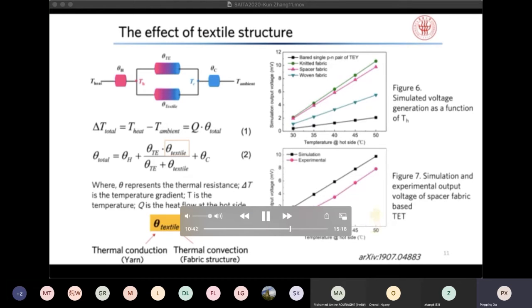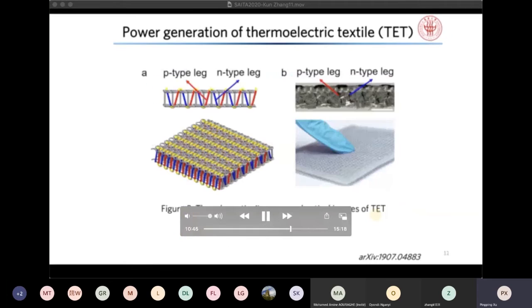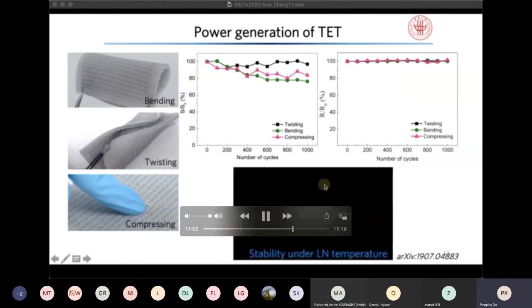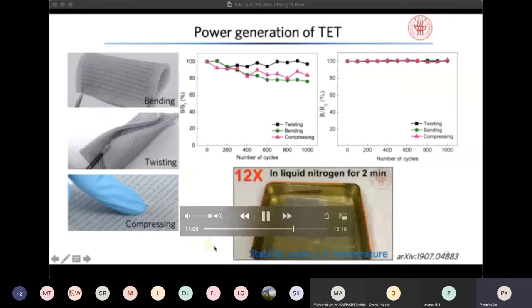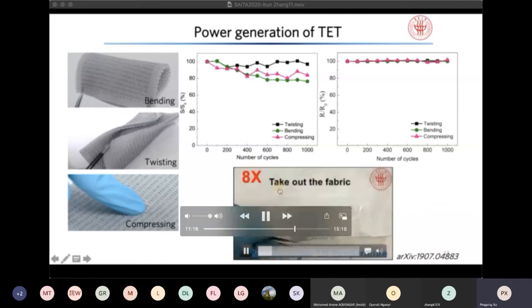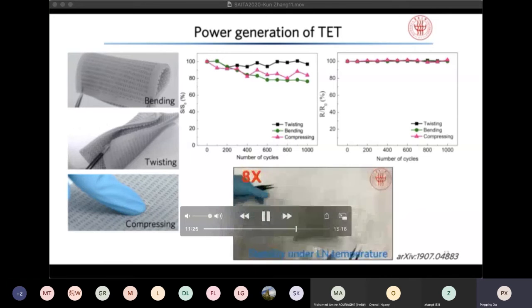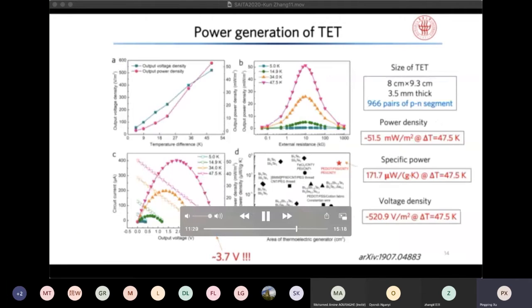As mentioned before, the actual structure of the textile-based thermoelectric generator shares a similar configuration to the conventional bulk organic thermoelectric generator. And the thermoelectric textile shows very flexible properties, and the performance is stable even after 1,000 cycles of bending, twisting, and compressing. Moreover, it shows excellent flexibility and functional stability at liquid nitrogen temperature, where a lithium-ion battery will be disabled due to frozen ion transport. And we then measure the power generation at different temperature differences and external resistances.